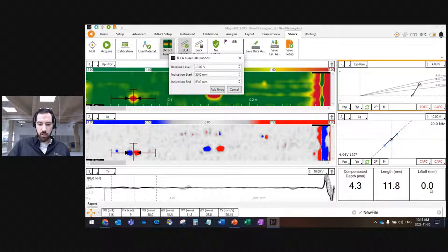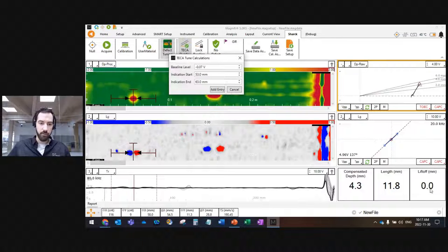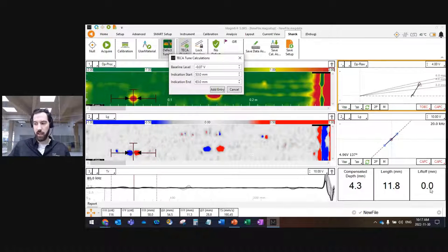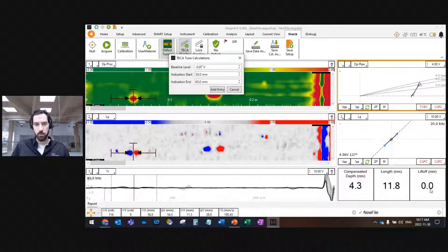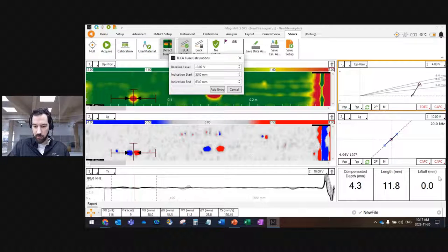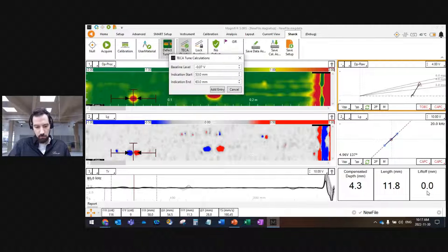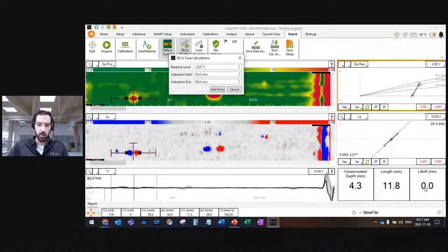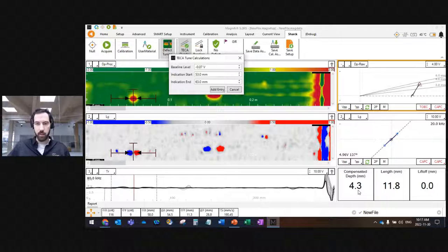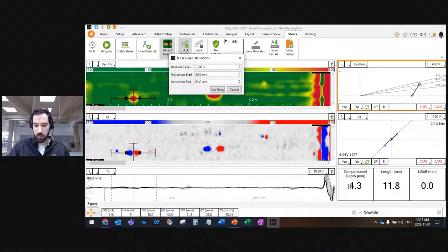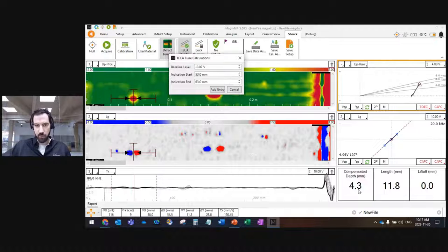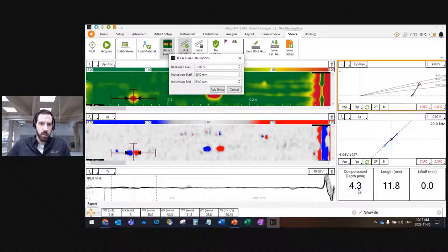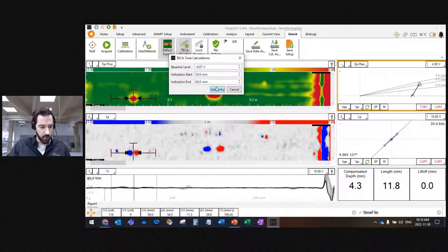Let me talk about this liftoff value because it's very important with Shark. Shark compensates for the properties of the material, but Shark also compensates for the liftoff. If you have a coating, an epoxy bonded coating, if you have paint, any type of material on top of your weld, you can still use Shark to inspect through it. The only difference is that here when it says liftoff, it will measure your liftoff. So if I have two millimeters of epoxy on top of my weld, you have a crack there, it's this depth, this length, but you also have a coating of two millimeters. What's really important is that the depth you're measuring will be compensated accordingly. The software knows how much liftoff there is, it will compensate everything accordingly to give you the real crack depth that you care about.